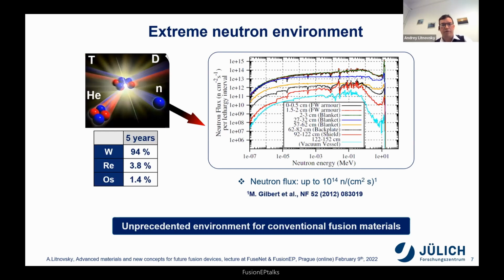Another characteristic feature of the fusion power plant, which distinguishes it from current fusion devices, is the neutron environment. As we remember, in the nuclear fusion reactor, the heavy isotopes of hydrogen, deuterium and tritium, will merge with the creation of helium ash, the fusion ash, a helium particle and a high-energy neutron. So the materials under this massive neutron impact will transmute, and after 5 years of operation, already 6% of tungsten will transmute to these isotopes.